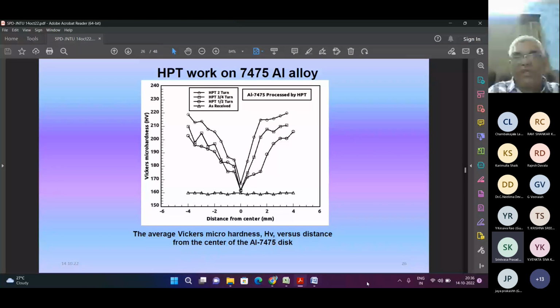So when you process with different loads, how the hardness changes, you can see where it is 160 and where it is 220 HV. There is a drastic difference between center and edge. The average micro hardness versus distance from the center of the aluminum 7475 alloy processed by 3/4 turn is presented here, and there is a drastic difference in the micro hardness values.